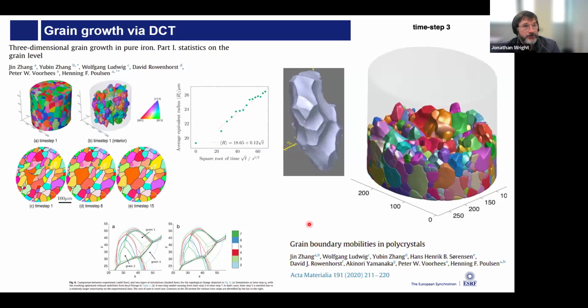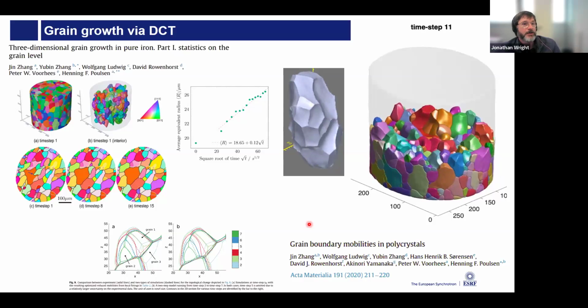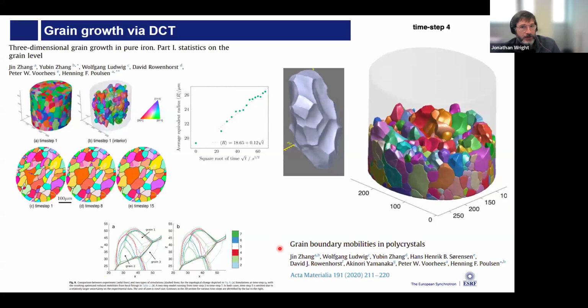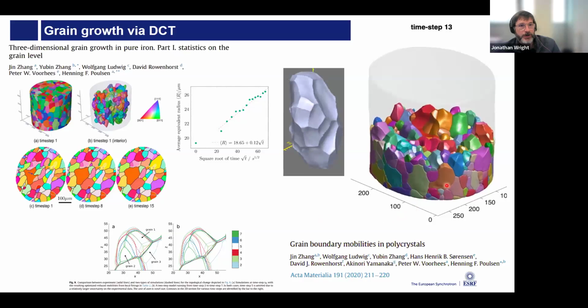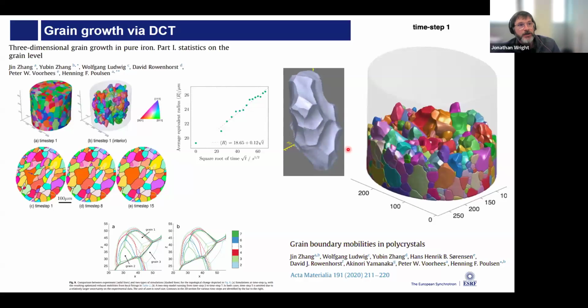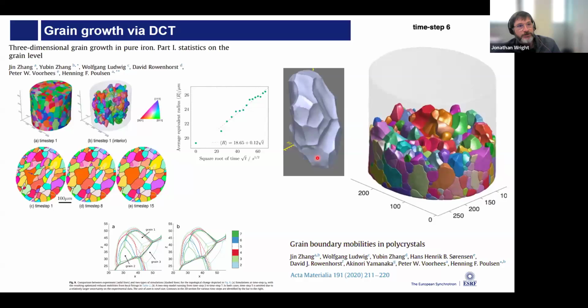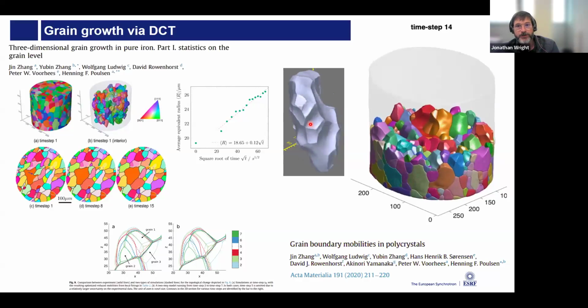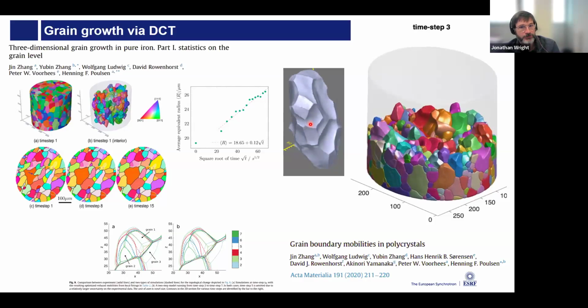I'll finish up with showing a video of our kind of fastest grain mapping method for 3D at the moment. So this is the case of undeformed grains. They're recrystallized grains that are growing. This is actually an experiment from before EBS, and it's the PhD of Jin Zhang. And they had 15 time steps, and they follow the evolution of the microstructure in this pure iron. So you see there's these very, very complicated grain shapes, and you have a movie of how all of these grain shapes are changing as a function of time.